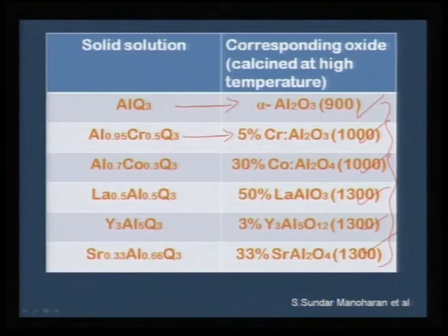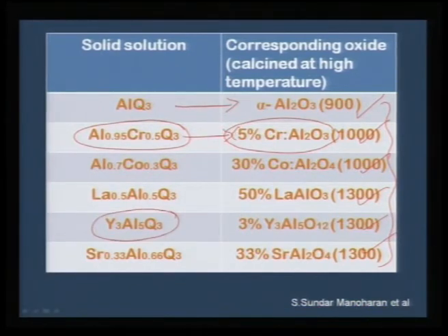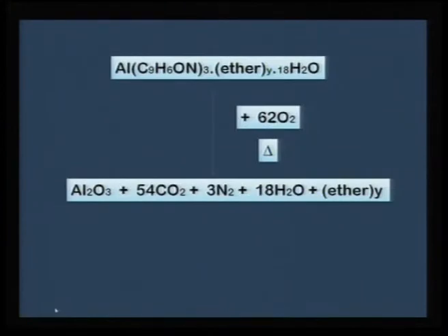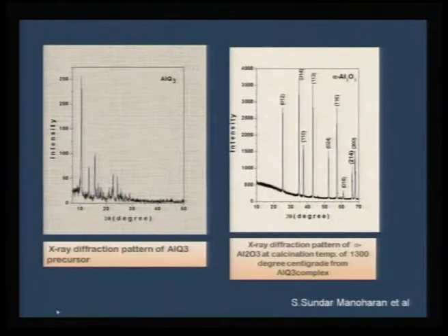If I am going to heat, for example, AlQ3 doped with chromium, then I am anticipating a ruby powder to come, which is less than 5% chromium doped Al2O3. Or if I am going to decompose this Y3Al5Q3, then I am going to look at YAG, which is nothing but a lasing material. Now you can see here, this is the protocol that we can follow. Take the precursor solution and then heat it in air. What you would expect is aluminum oxide, and for the other ones the corresponding metal oxides.